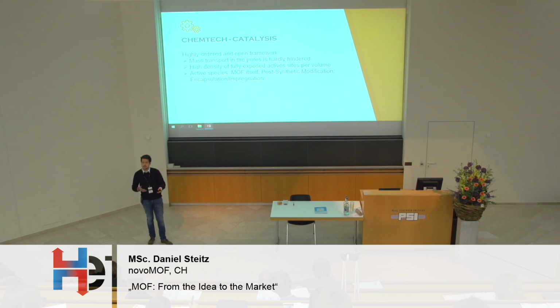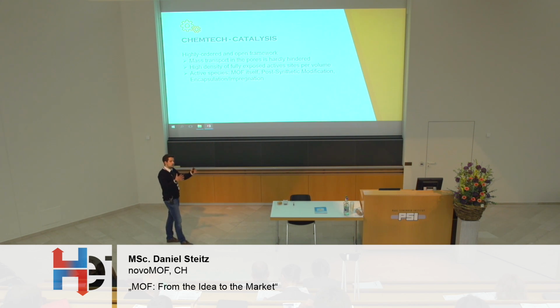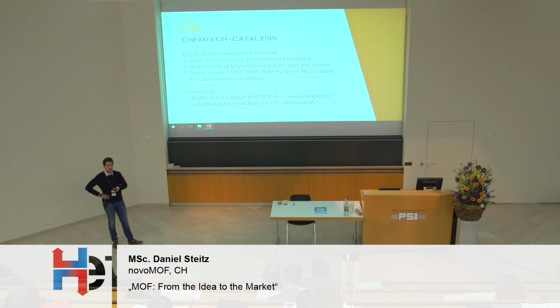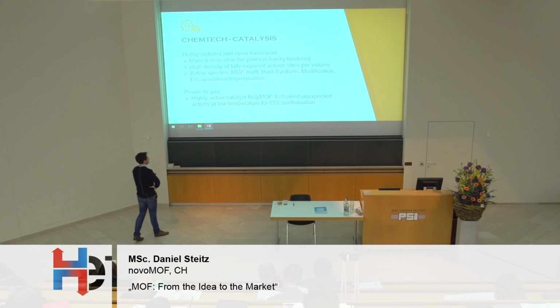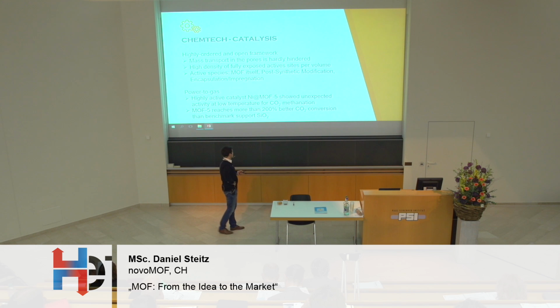Then, of course, the active species can be at different locations within the MOF. First of all, the metal of the MOF itself can, for example, be the active species, but it could also be connected to the ligands, by post-synthetic modification, or simply by taking the active species and growing the MOF around this material, encapsulating and immobilizing it. And there's just one example, power to gas, where a study was able to show that a catalyst system based on MOF showed twice the CO2 conversion rate compared to a benchmark support like SiO2.